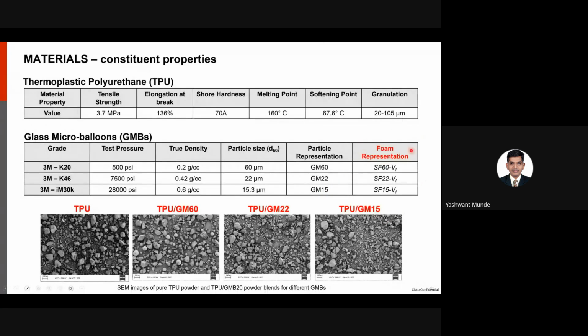For the syntactic foam that we print, we use this nomenclature. SF stands for syntactic foam. The first number here is the particle size, that is 60, 22, and 15. Dash VF is the volume fraction of these individual particles that we add to the TPU powder. As you can see here, we chose particles. TPU is in powder form, and these microballoons are also powder-like structures.